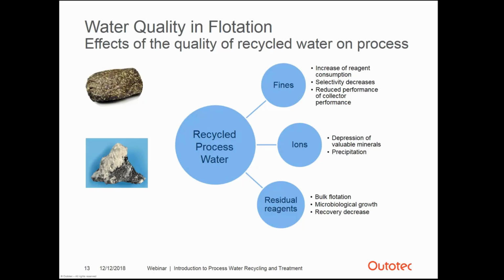Gold flotation, you see the ore here on top left. Gold flotation is very sensitive to fines and ions, especially calcium ions, which can depress free gold. Also, cyanides have been noticed to depress gold flotation by increasing the solubility of metal xanthates and preventing adsorption of collector on the surface of mineral particles.